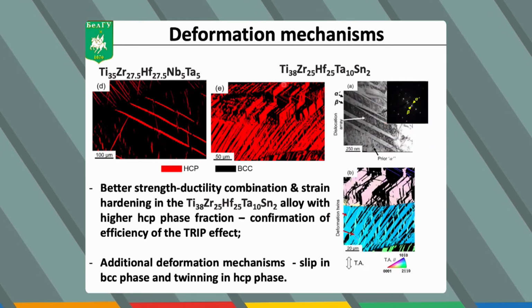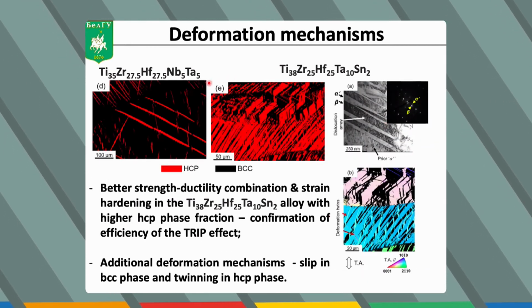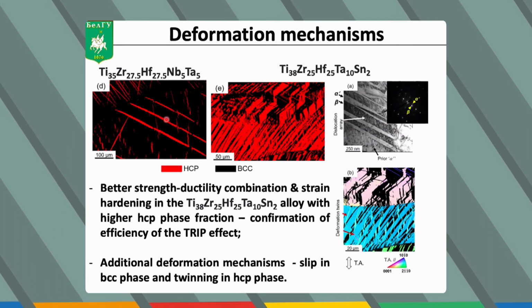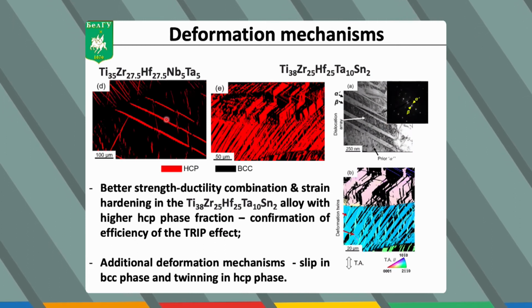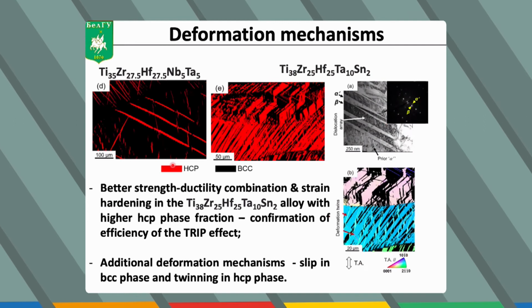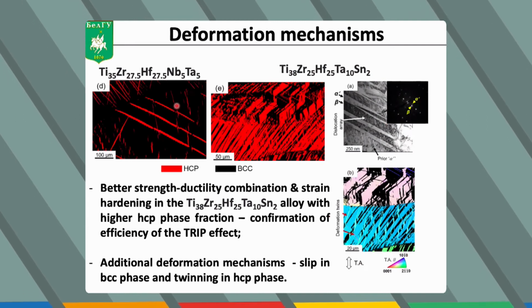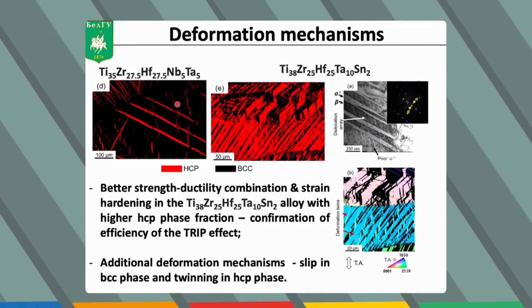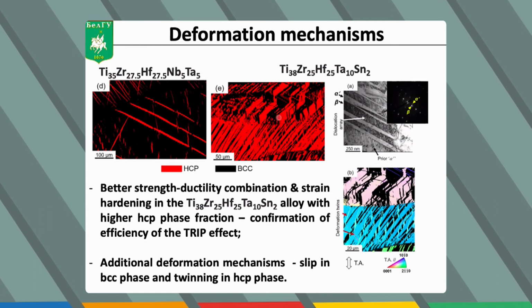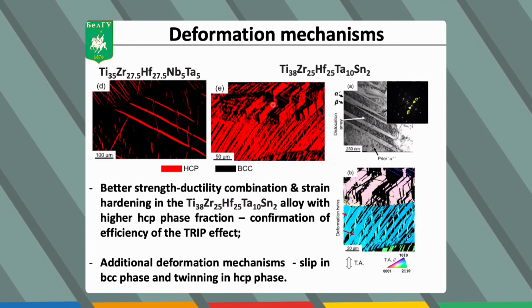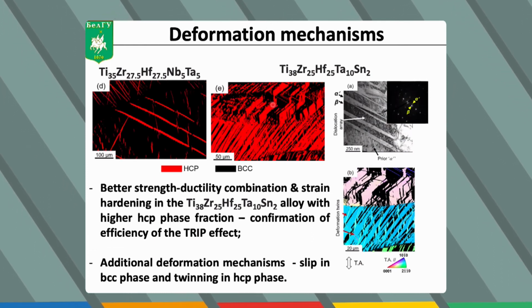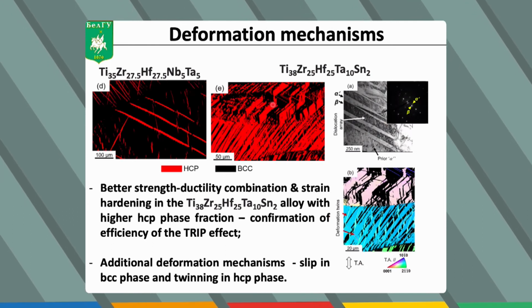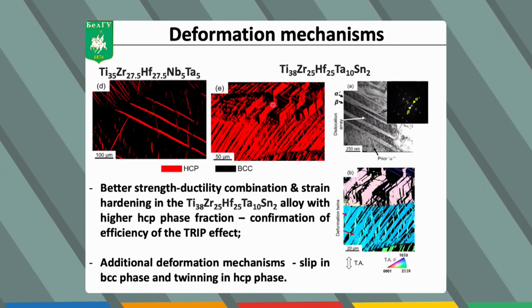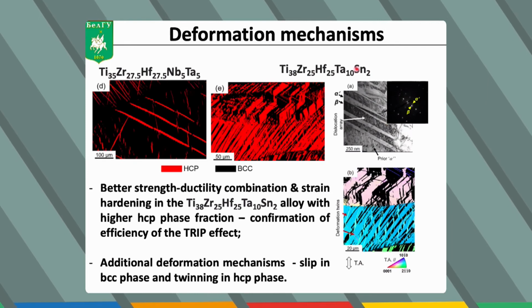And here are the deformation microstructures. Here in these maps, the martensitic phase, the HCP phase, is shown in red, and clearly there is much more martensite in the alloy with tin. So it's the indication that the transformation-induced plasticity effect is indeed responsible for the improved properties of these alloys.